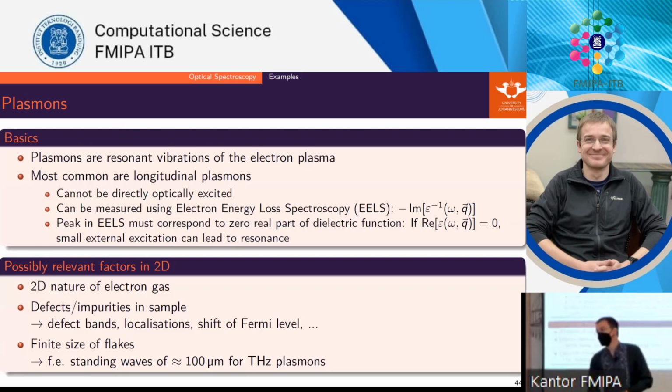Okay, we can also do plasmonics with this information. So plasmonics is basically the collective motion of the electron gas. That can be interesting for a number of reasons. My favorite reason is chemical sensing. So basically every material has a frequency. I don't know whether every material has a frequency, but basically there's a frequency of the material. If you put the energy of this frequency in via light, for example, you can excite an electron wave. So the electron gas will just oscillate. And what happens is if you have an adsorbent on the surface of this material, that energy changes, right? So you can tune the resonance with the adsorbent.